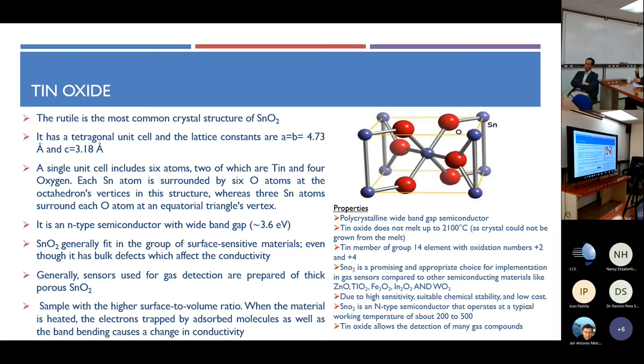Due to its high sensitivity, suitable chemical stability and low cost, it is an n-type semiconductor and operates at a working temperature of 200 to 500 degrees Celsius. Tin oxide has a rutile structure, a tetragonal unit cell, where the tin is surrounded by 6 atoms of oxygen, and it has a good band gap of 3.6 electron volts. It fits as a surface sensitive material, though it has bulk properties.